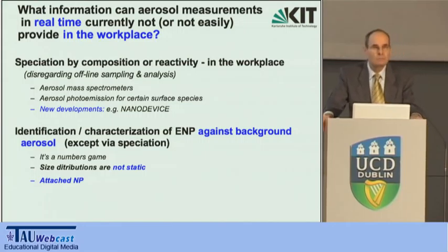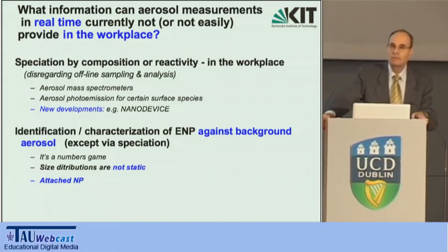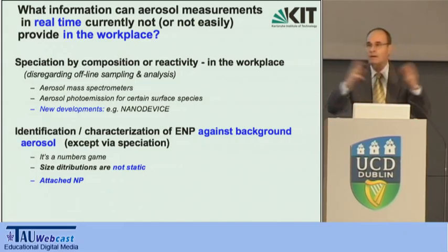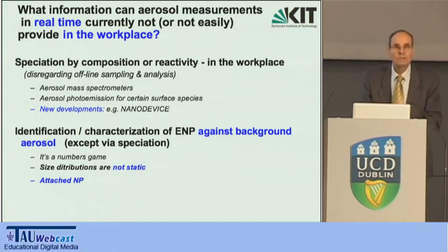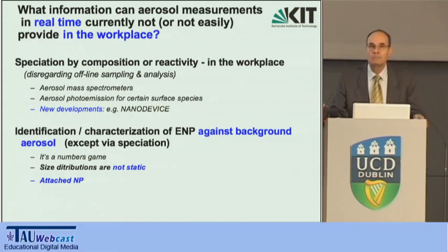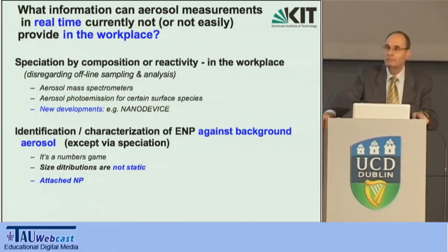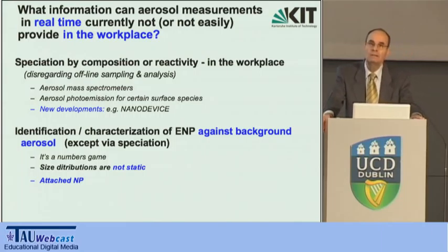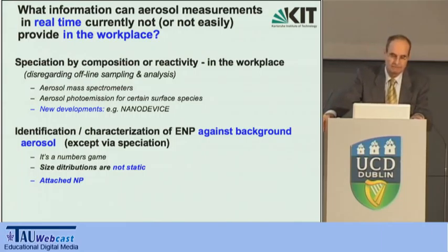There are a few cases where ENP or, let's say, human industrial activity really produces strong source strengths, such as transfilling, for example. If you take a powder and you move it into another container, or cleaning up a spill, indeed, there you can really have appreciable concentrations. But otherwise, in a reasonably controlled manufacturing environment, unless you have a big leak with an accidental release, you don't have many nanoparticles. So how are you going to find those small doses of particles?